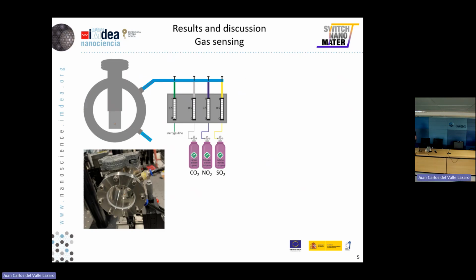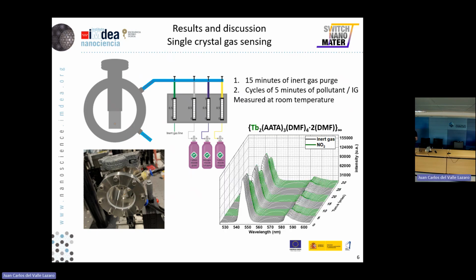After this photochemical characterization, we proceeded to the gas pollutant sensing measurements. We introduced the samples in the same vacuum chamber and purged it with 15 minutes of inert gas, then cycled with 5 minutes of pollutant and inert gas at room temperature, obtaining this type of results where we can see that the maximum emission of the lanthanide suffers a modification in the emission intensity of its luminescence while the pollutant is inside the chamber.